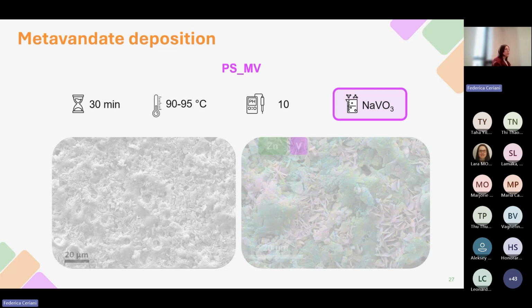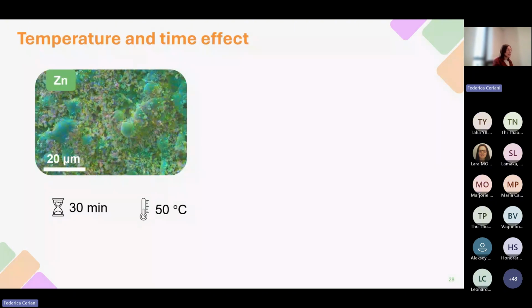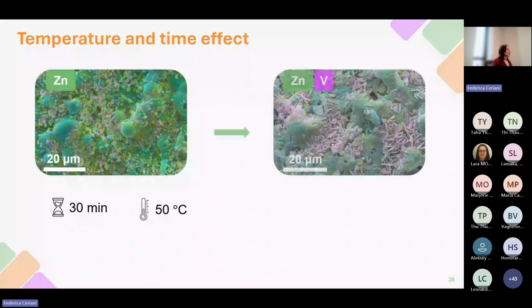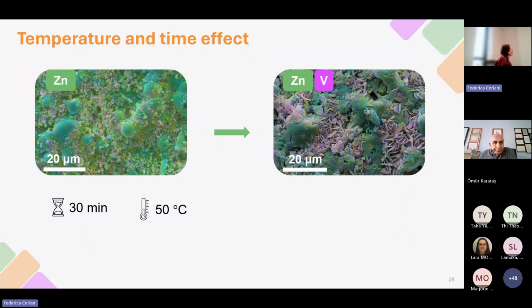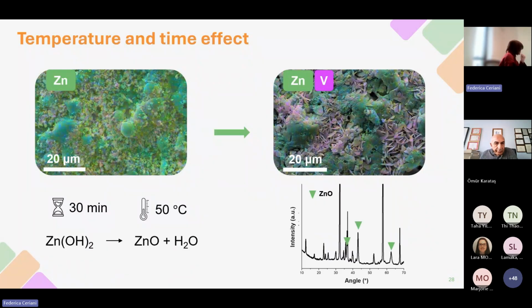To understand why the morphology changed from the one observed for the PS30 sample, characterized by the presence of small lamellas, to the one described for the PS metavanadate sample, we have to think about the temperature effect on the zinc precipitates. Indeed, when the PS30 sample is exposed for 30 minutes to a solution heated to 50 Celsius degree, zinc hydroxide precipitates are almost completely converted into zinc oxide structure, as confirmed also by means of XRD analysis. And as I said before, zinc oxide is characterized by petal structure, that is the one observed for the PS metavanadate sample.